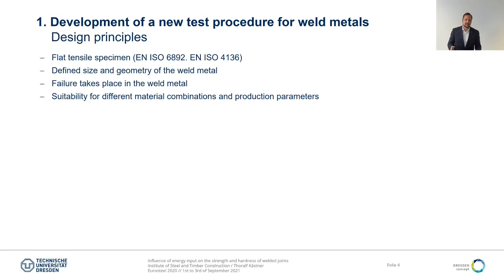We wanted to have a flat tensile specimen for a really easy execution of the test. We needed a defined size and geometry of the weld to easily determine the strength and the stresses which are acting within the weld metal. And the failure needed to take place in the weld metal, because only then can we transfer those results to the component level. Otherwise, when the failure takes place in the base metal, for example, we cannot transfer those results because we just know, okay, our weld metal has a higher strength than the base metal, but we do not know the exact strength of our weld metal.